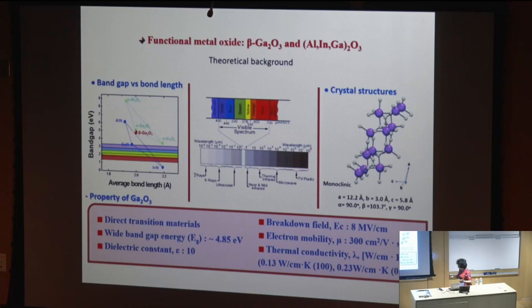What is that? Again, the semiconductor, III-VI oxide, gallium oxide. It showed that the gallium oxide, first of all, is polymorph, and that is the material that we have known for a long time. But they came to me again, asked me to be involved. Because if you look at aluminum gallium nitride, the band gap as a function of the lattice parameter, that is aluminum gallium nitride. But if we go to the gallium oxide and do the atomic gap engineering with the aluminum, we can have larger wavelength again. And the beauty is they are semiconductors with direct gap, and at the same time a large lattice parameter and large energy gap.